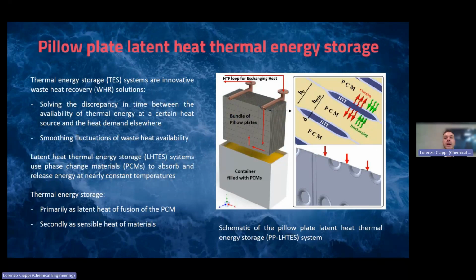The analysis that was conducted considered thermal energy storage based on pillow plates and latent heat transfer. The system comprises a set of plates with a specific geometry that is called pillow plate. As we can see in the image, they have a wavy surface that is obtained by hydroforming two metal sheets that are connected through linear weldings and circular weldings. In this way, it's possible to obtain an internal channel inside the plates that drives the heat transfer fluid inside the plate and increases the turbulence of the fluid itself.